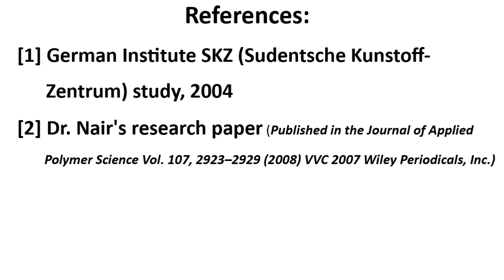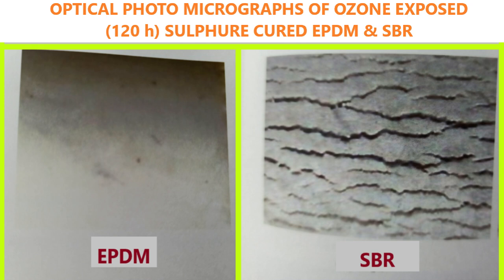My own research on the aging properties of EPDM has shown its excellent resistance to ozone, heat, water, and gamma radiation. Please see reference 2. As per ASTM D471, maximum water absorption permitted on EPDM roofing membrane is 9%, but the study showed that EPDM absorbed just 0.4% water and that no ozone cracks developed on ozone exposed EPDM even after the exposure of 120 hours. Resistance to heat and gamma radiations were also excellent in EPDM. This makes EPDM an ideal material for roofing membranes.